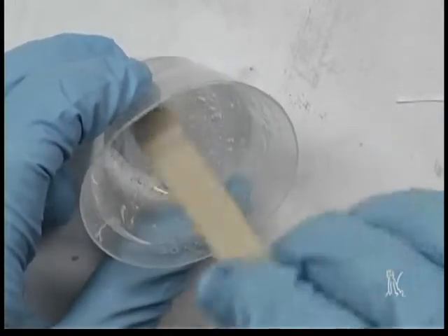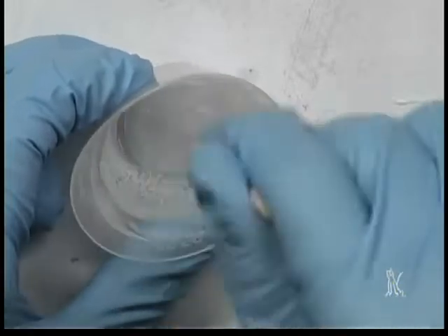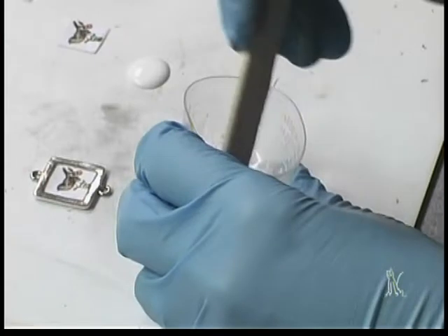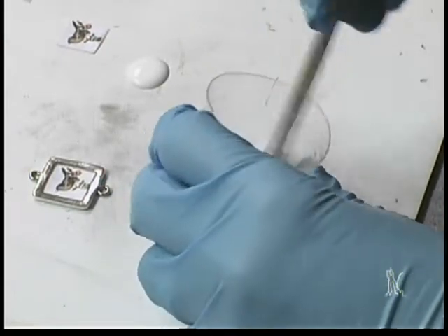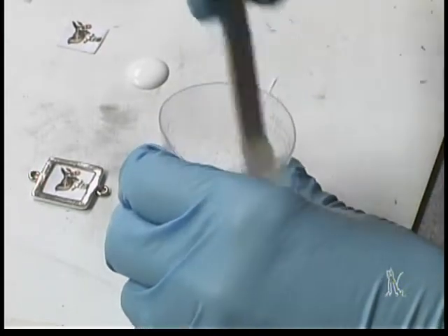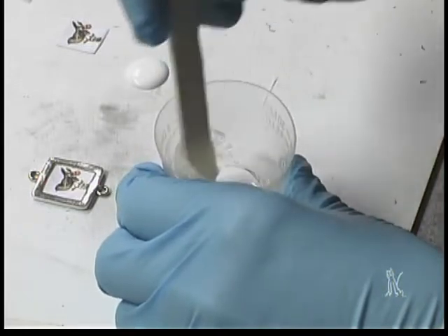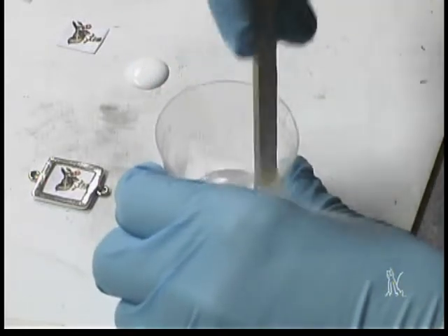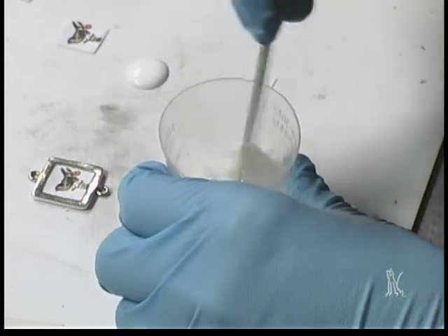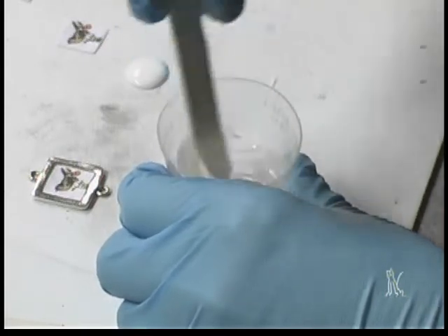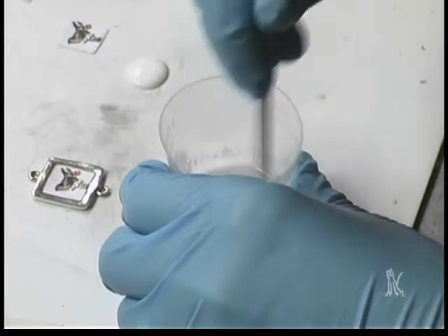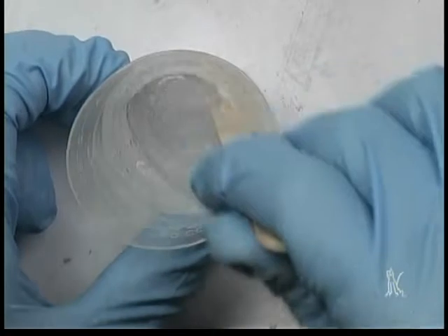If there's just the slightest bit caught in the corner of the cup or on the side of the cup that's not thoroughly mixed in, then you have problems with your resin not curing. So I'm going to just keep working on this. And you scrape the sides of the cup, and you want to do a stirring motion instead of a whipping motion because you don't want too many air bubbles. I've got a few in there now that I can get those out in a minute. And you have about close to an hour's working time with this resin, so you don't have to worry about being in a rush that it'll set up too quickly. You really want your project to be successful.